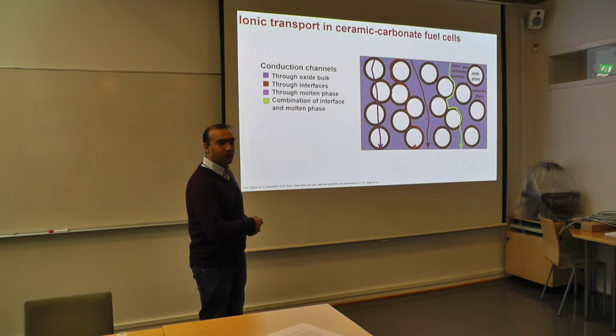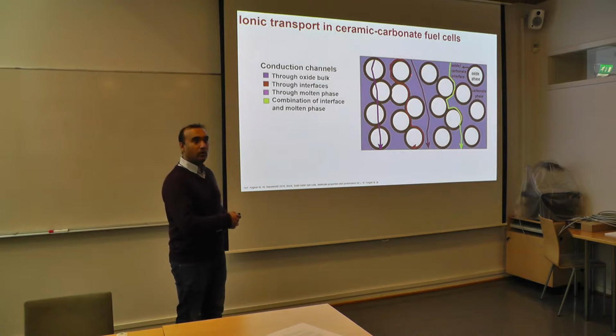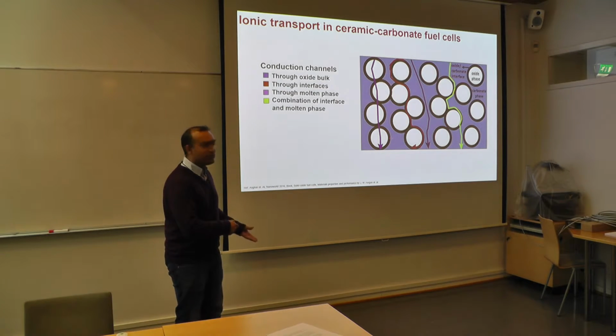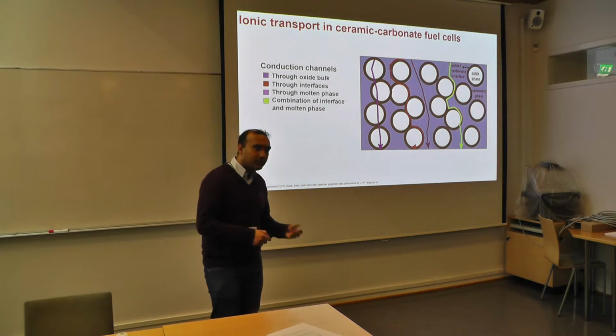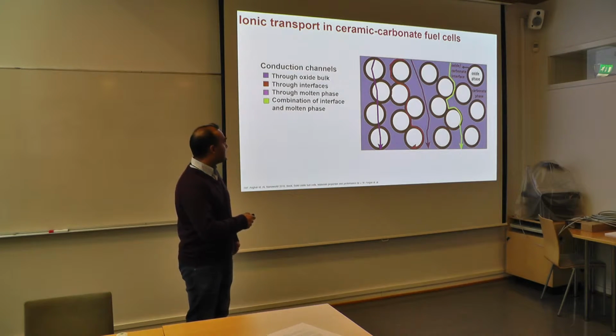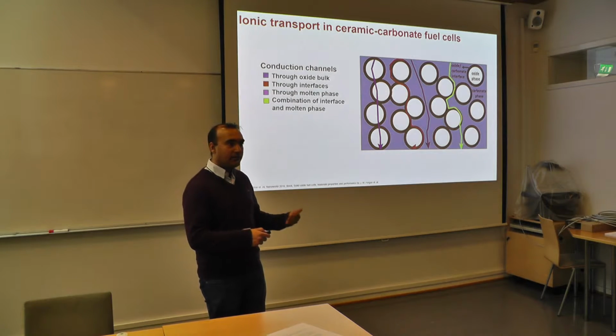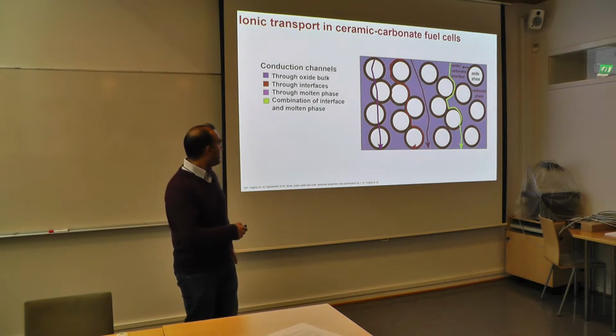So now the ions move through different channels. For example, the oxygen ions move through the vacancies in the bulk of these oxides, like in the case of a solid oxide fuel cell. But now we also have carbonate ions, which can just flow in the electrolyte, in the carbonate. They can go through this layer, or they can transport through the interface, or a combination of those. So there are different channels. And from the literature and from our experiments, it seems to us that these interfaces are very crucial for the ionic conduction here. So it means that we need to have an optimized composition to get higher performance.